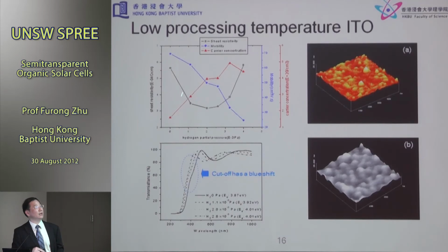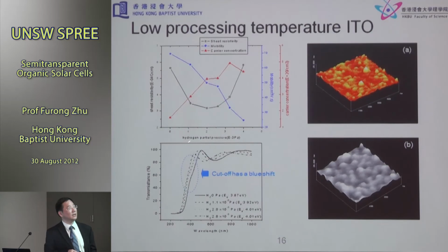So this is the carrier concentration and mobility of the ITO film prepared at different conditions. And the whole idea here is that we include using reducing gas species during ITO fabrication.